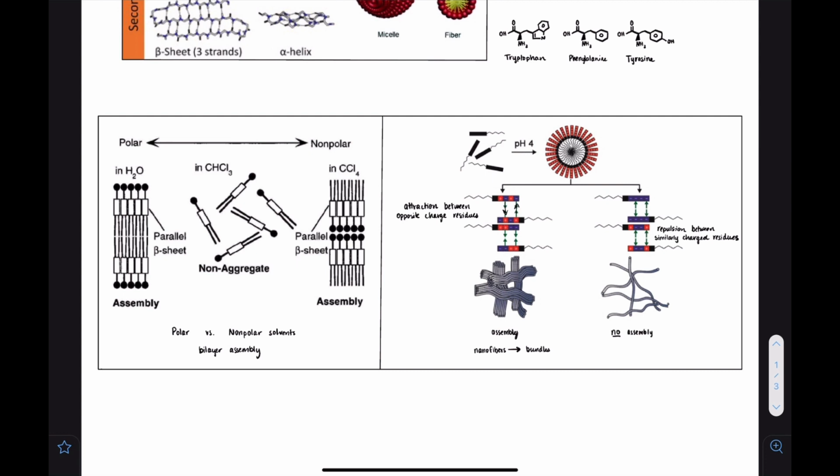On the other hand, pH can also have an impact on the formation of structures, especially with modified peptide amphiphiles including charged groups. In this figure here, nanofibers form when pH is greater than the pKa, but changes in pH are affecting the ability of the nanofibers to bundle.